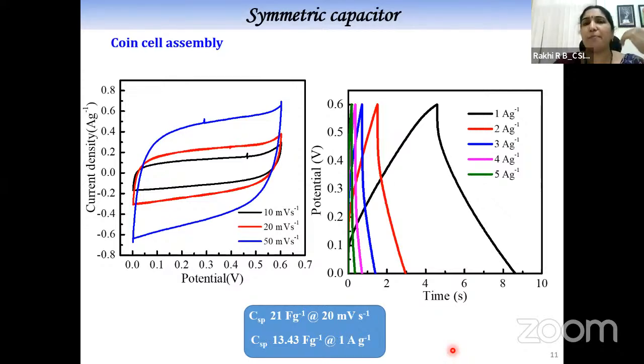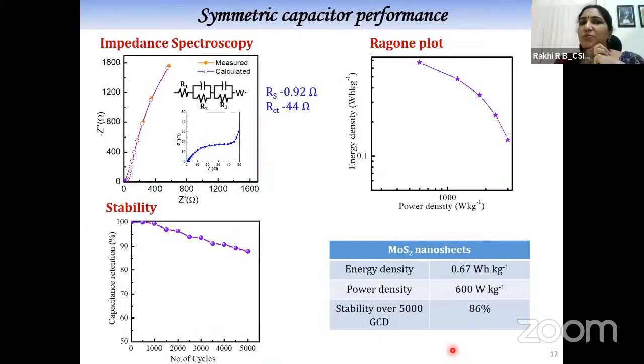So when we compare this value with other devices, it is very, very small. We also did other supercapacitor measurements like impedance spectroscopy to find the RCT, the charge transfer resistance, which was quite high. It was 44 ohms, which is too high for a supercapacitor device. Then we found the energy density and power density plot, known as the Ragone plot, and the cyclic stability was only 86% after 5,000 cycles. It is not a desirable value for a supercapacitor. So we found that this top-down approach won't work. It is not as good as any other state-of-the-art material.